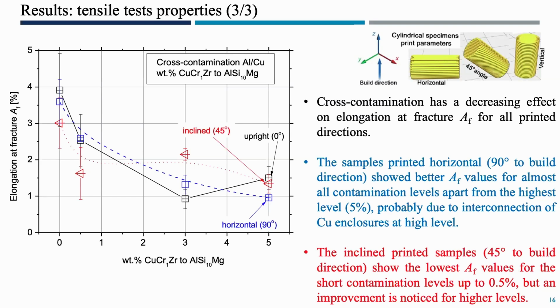The most interesting results come from ductility, tensile elongation at fracture, showing that all contaminations have a poor effect on tensile ductility. And this is something that we expected, since the contamination actually acts more or less as stress raisers. And this decreases the tensile ductility.